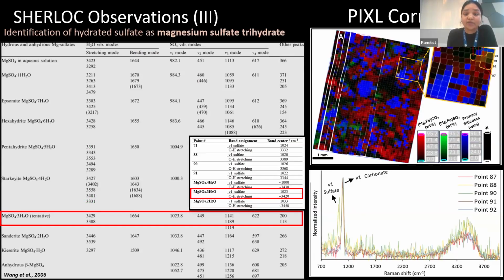To identify what type of hydrated sulfate we see here, we compared the fitted wave numbers in SHERLOC data with various sulfate peak center and hydrated bands in the literature. And we found that it matches nicely with magnesium sulfate trihydrate. Out of many hydrated magnesium sulfate species, we shortlisted 3: dihydrate, trihydrate, and tetrahydrate. Based on V1 peak center, as we see in this little table here, dihydrate was too high and tetrahydrate was too low. So we concluded that it should be trihydrate, which was the closest match, and also consistent with previous findings in the delta top studies.